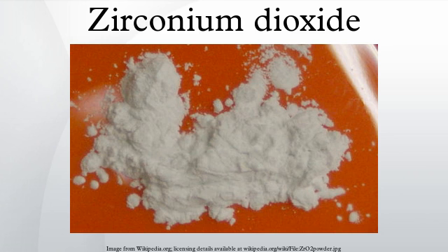If sufficient quantities of the metastable tetragonal phase are present, then an applied stress, magnified by the stress concentration at a crack tip, can cause the tetragonal phase to convert to monoclinic, with the associated volume expansion. This phase transformation can then put the crack into compression, retarding its growth, and enhancing the fracture toughness. This mechanism is known as transformation toughening, and significantly extends the reliability and lifetime of products made with stabilized zirconia.